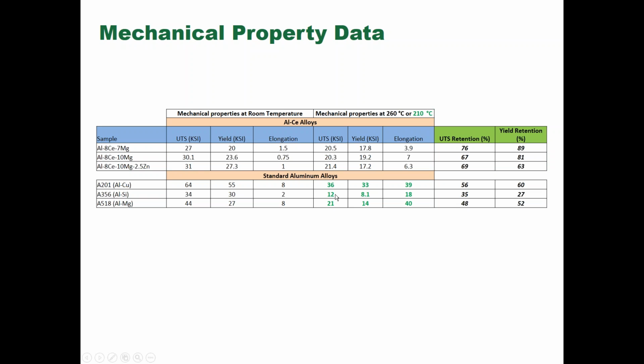But alloys like 356 at 210 degrees, they really continue to fall apart. And if you look at the ultimate tensile strength retention, it's only 35% in 356. It's 56% in 201 and about 50% in 518, which is another aluminum mag alloy. So you have very, very stable mechanical properties as you add cerium to the alloys, and you improve the room temperature mechanical properties if you add magnesium as just an example element.